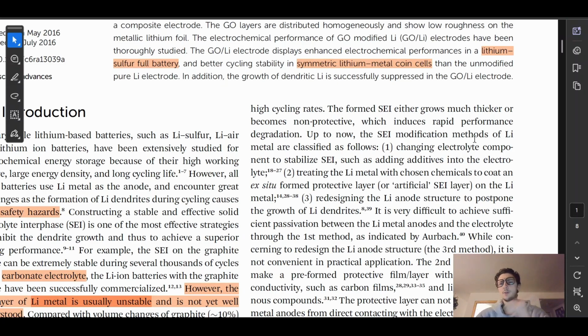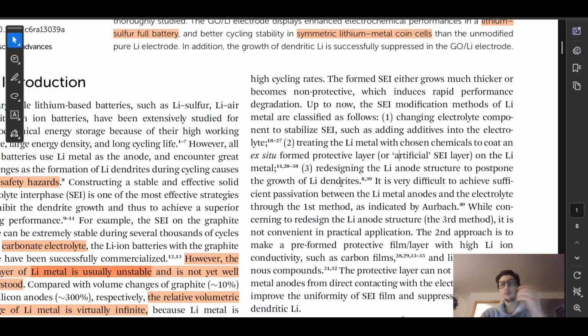Up to now, the SEI modification methods of lithium metal are classified as follows. 1. Changing electrolyte component to stabilize SEI, such as adding additives into the electrolyte. 2. Treating the lithium metal with chosen chemicals to coat an ex situ formed protective layer, or artificial, so I guess ex situ is artificial, on the lithium metal. 3. Redesigning the lithium anode structure to postpone the growth of lithium dendrites.